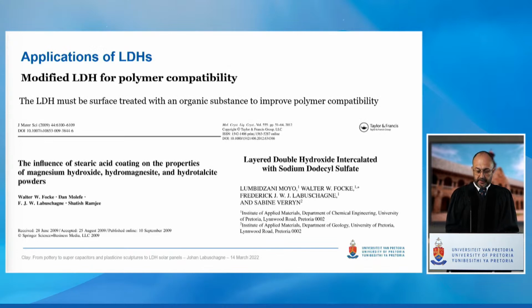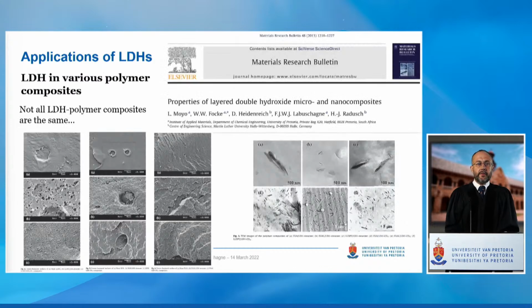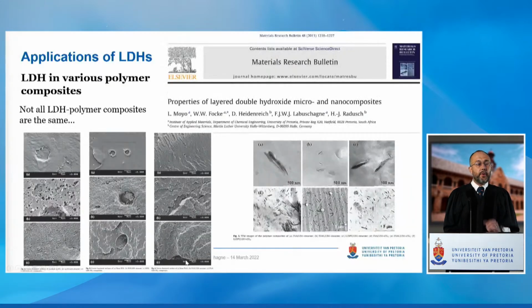This helped get polymer compatibility, which was really important. On this slide, I show a publication in which we investigated different modifications of LDH into different polymers. So these slides, that is one polymer, second polymer, third polymer. And the polymers we used were polyethylene, polyvinyl alcohol, and polyvinyl acetate. And not all polymers are the same. We could see from the results that we got different mechanical properties for the different modifications and the clay in the different polymers.